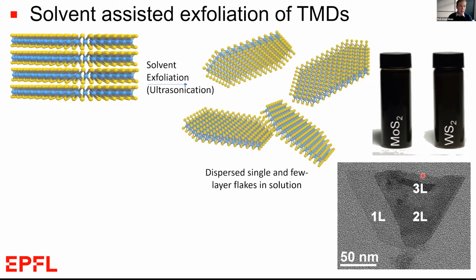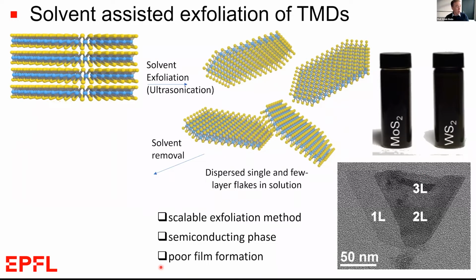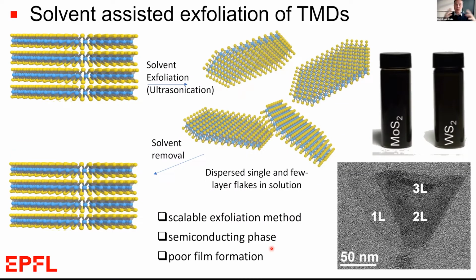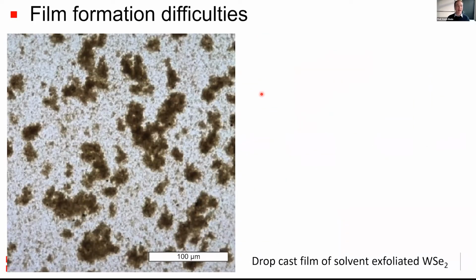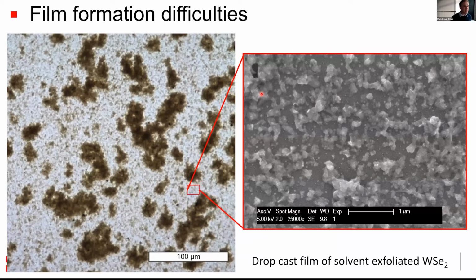But a problem that we noticed when we tried to do this in our lab was we had very poor film formation. And that's because when we remove the solvent, the van der Waals forces between these basal planes of these flakes want the flakes to restack and aggregate. And just to illustrate that, here's an optical microscope image and SEM image of a drop cast film that we tried to make in our lab a few years ago. And you can see these big aggregates of the material that we've made.